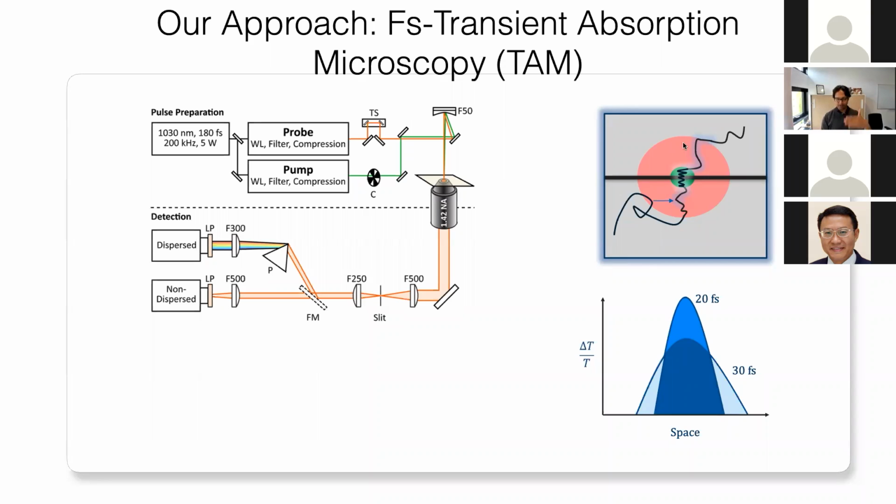And then we come in at various time delays after that, say at 2 femtoseconds, 5 femtoseconds, 10 femtoseconds, etc., out to nanosecond time scale, with a probe pulse represented by this pink area here. But the probe pulse is now wide field. So that will then go on to a CCD camera, and we image this entire area, right? And so what we see at very early times, you'll basically image this profile of excitons that you have created in your material, right? And that might look something like this. So this is the profile in the top blue color here, that you might image.